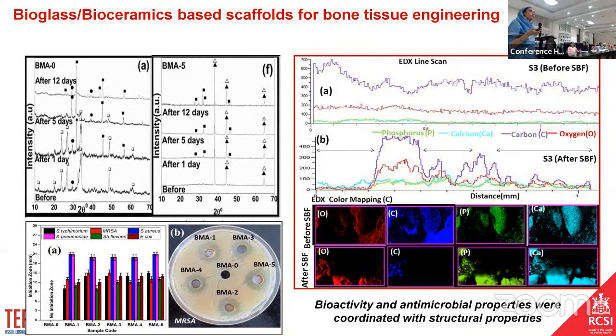And third, we also check the antibacterial effect, because at the end, this material will go into the body. And if it has an immune response, the body will not accept it as its own part. So we check its antibacterial effect with different microorganisms. Here I'm showing it with MRSA, which is the most resistant strain for any drug. So you can see these black circles. This means my material is inhibiting the growth of bacteria in this range. So we check all these parameters.